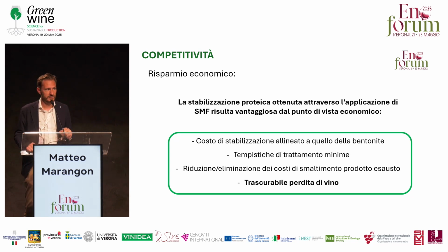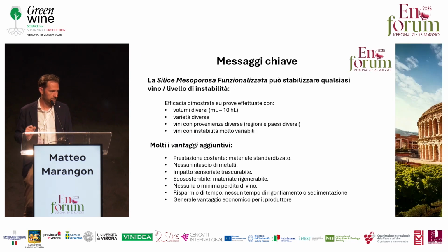Plus, as Gianni said, no loss of wine. It is a negligible loss. You see, with bentonite, you have 3 to 5% of wines trapped in the lees, and that is a huge economic loss, while in this case, you do not have a loss. This is the major economic advantage.